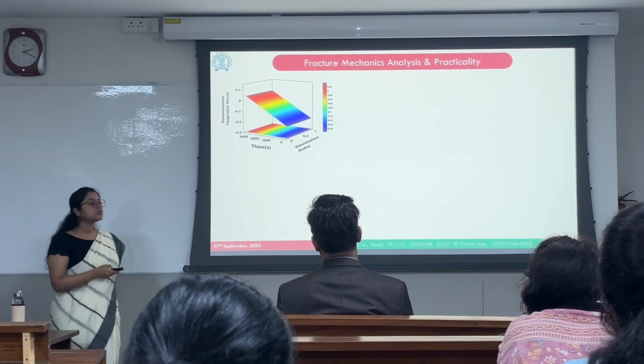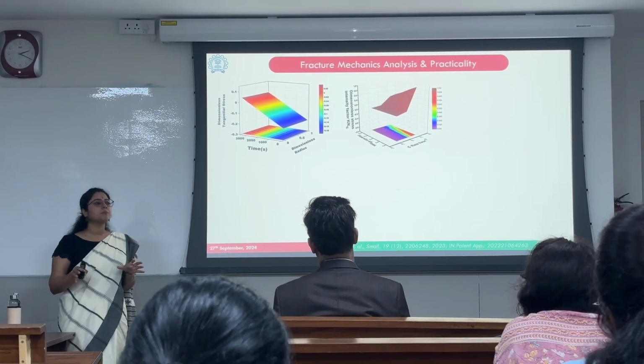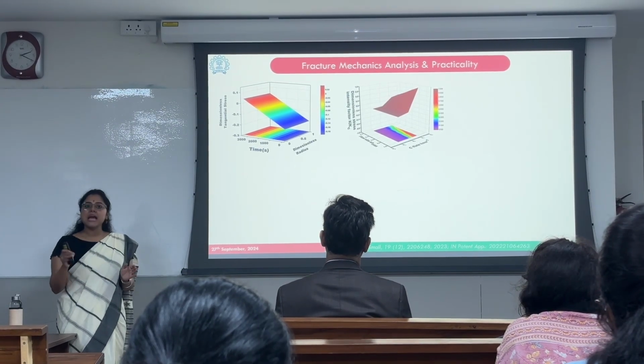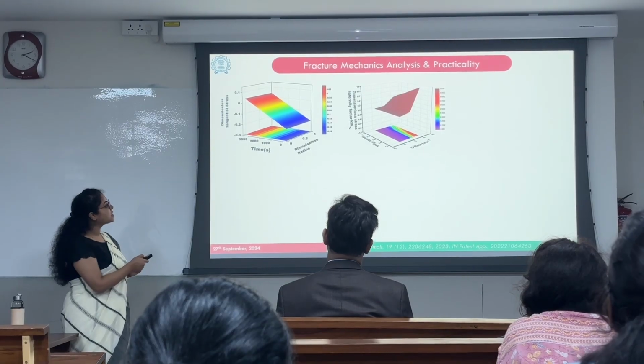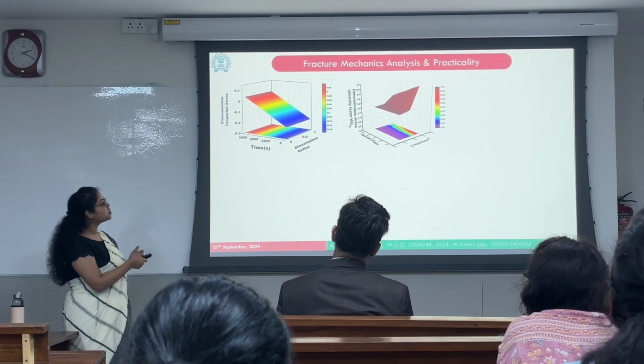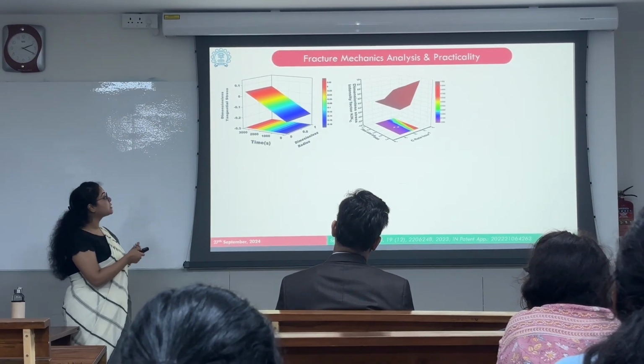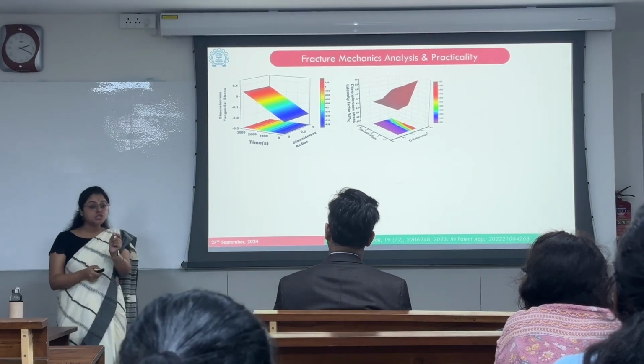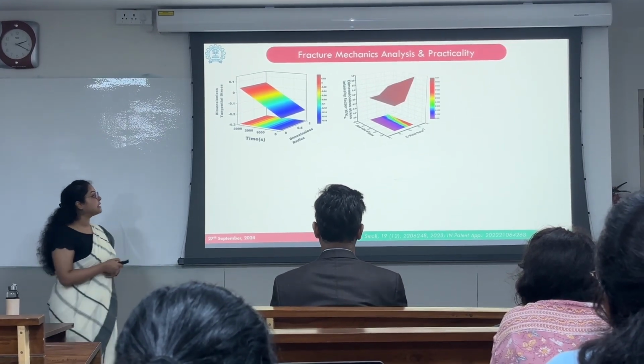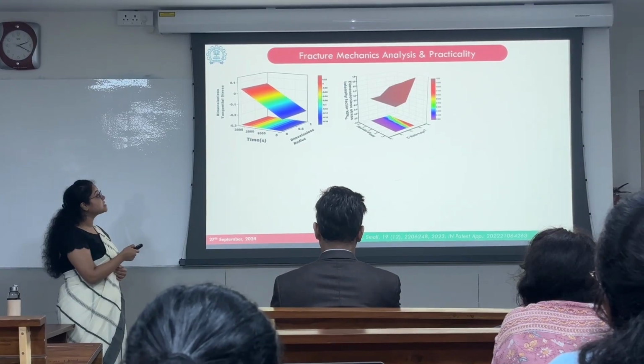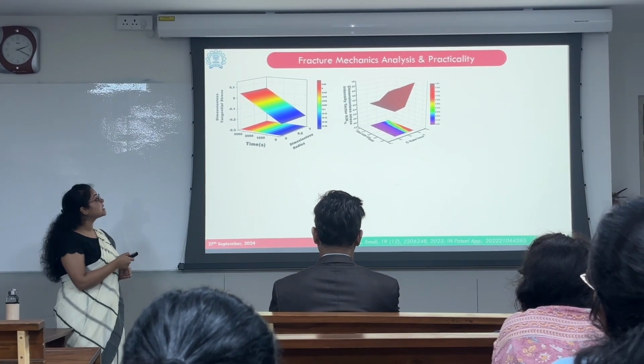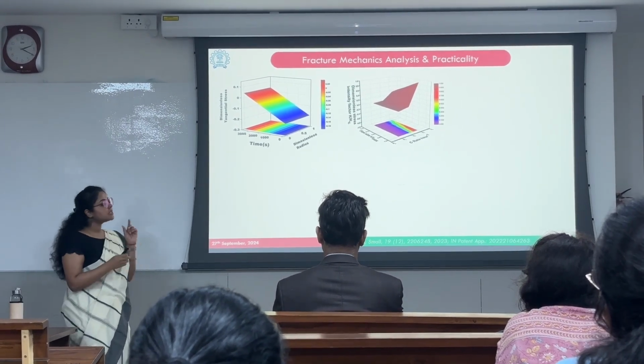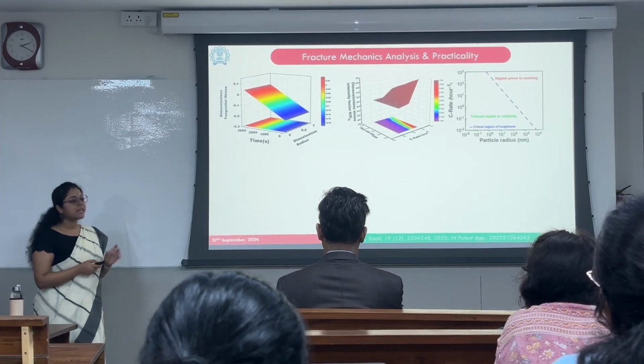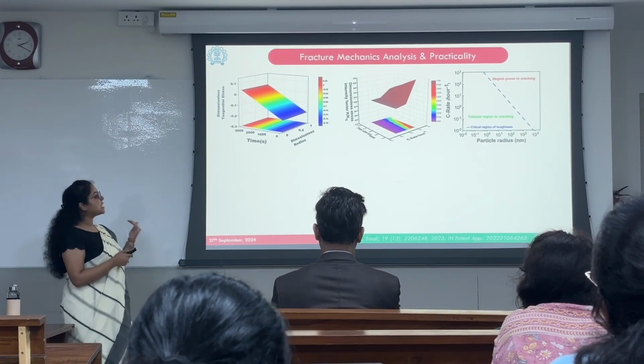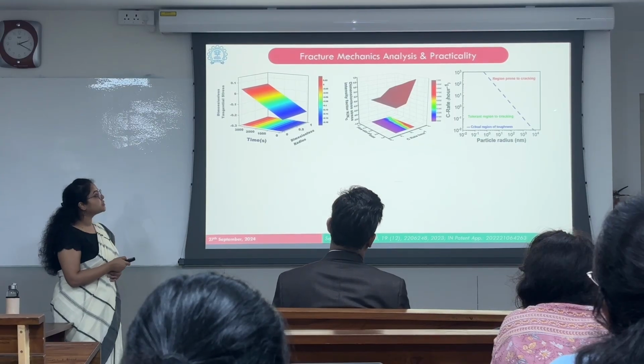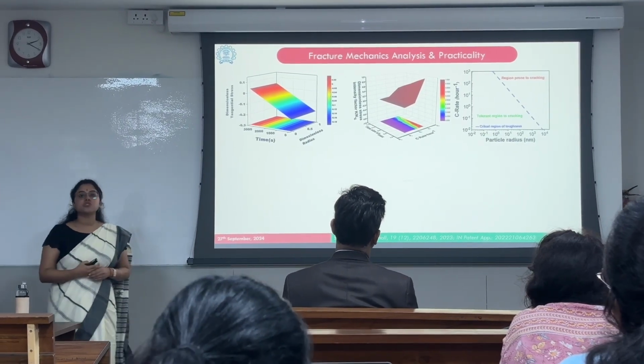To understand the effect of the C rate, we considered two extreme particles of 25,000 nanometer and 500 nanometer. The 25,000 nanometer particle has been shown here, which shows that with increase in C rate, the flaw size, which is basically the initiation of the exfoliation and cracking, is increasing, and the stress intensity factor is seen to be increasing exponentially. To conclude this analysis, we predicted an electrochemical shock map, which tells us about the critical region of toughness for this kind of layered oxide structures.